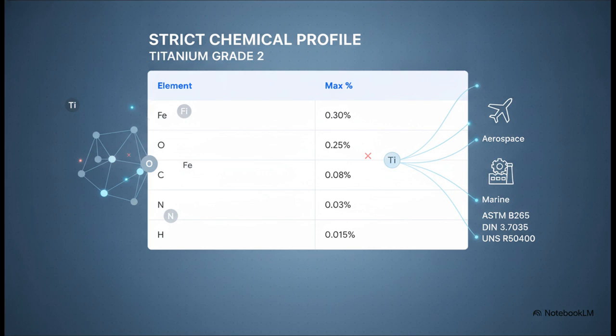To guarantee international compliance with aerospace, marine, and industrial standards like ASTM B265, DIN 3.7035, and UNS R50400, the composition has to be heavily weighted with a balance of minimum 99.2% titanium. Trace elements are tightly capped: iron at a maximum of 0.30%, oxygen at 0.25%, carbon at 0.08%, and nitrogen at 0.03%. But most notably, hydrogen is restricted to a tiny maximum of just 0.015%.